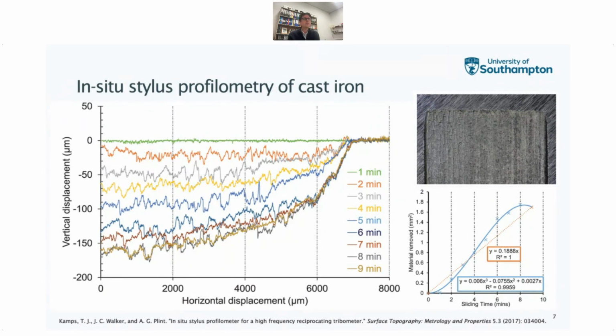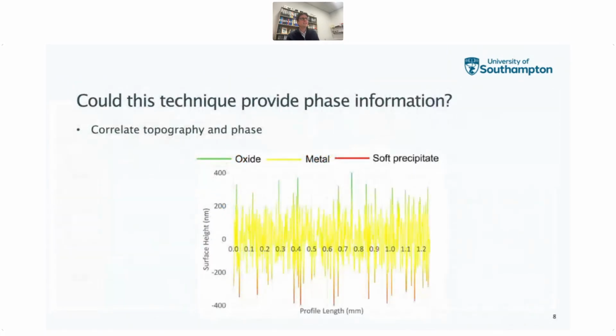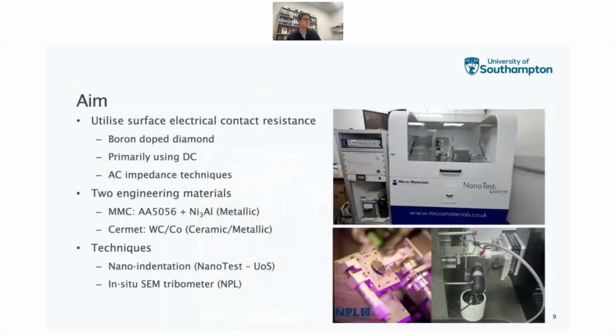So we then supposed that if we could have a stylus that traverses the surface to get the metrological information, could we somehow functionalize that and get some information about the phases that might be present on that surface? And really, that was the inspiration for this project, as to whether we could distinguish between different areas of the surface that might perhaps be insulating or conductive or exhibit different phases, and that was the premise of what we attempted.